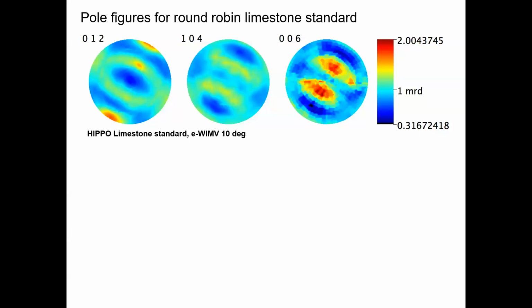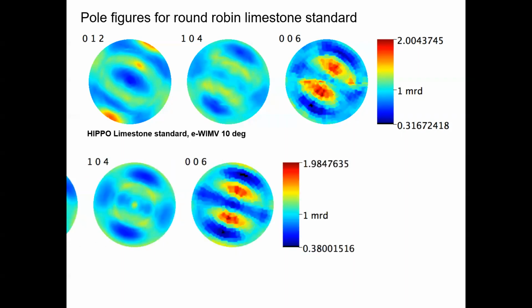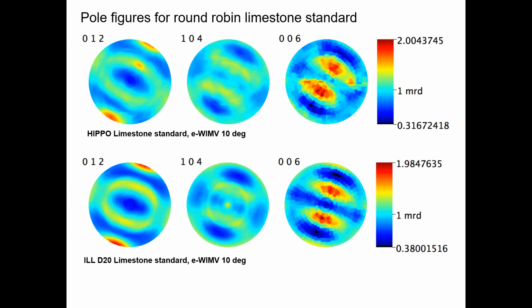Here is an example of HIPPO data collected and compared with data for, this is again this round robin limestone, with data for ILL, now the D20, a more recent diffractometer, and you see again a very similar pattern, except that if you look at the HIPPO measured this one on top in 20 minutes, while in ILL it took about 4 hours.